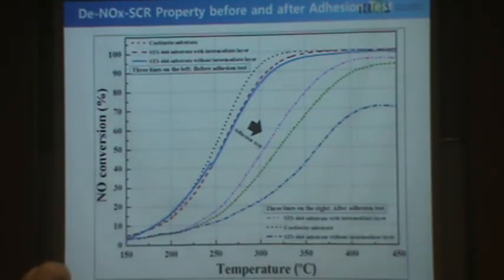And we tested the NO conversion. And this one, cordierite, these three are before the adhesion test, and these three are after the adhesion test. The cordierite sample was the best, showing the best NOx performance. And the stainless steel substrate sample is a little lower in NOx performance. But after the adhesion test, the samples with the intermediate layer showed the highest NOx performance.